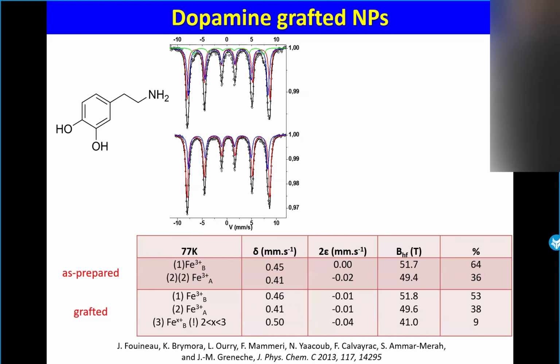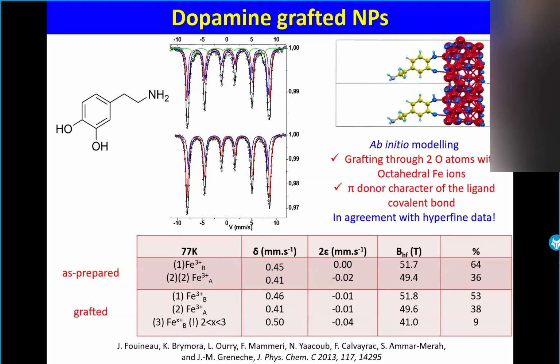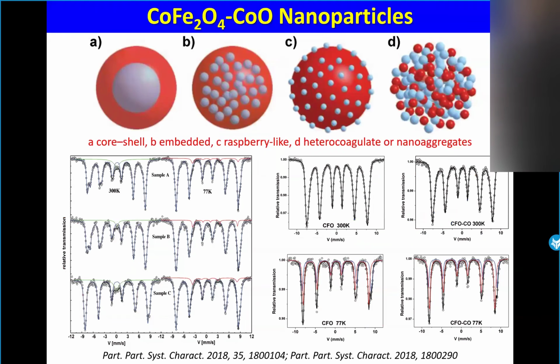The isomer shift is a bit higher. That means you have electron transfer. Then you can see that there is a decrease of one component much more than the other one. In fact, it indicates that the dopamine sits on octahedral sites, not on tetrahedral sites. By DFT, it was possible to confirm these different results. I am close to the end.